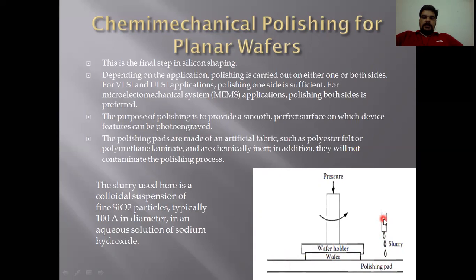These polishing pads are made of basically artificial fabrics such as polyester felt, or you can use polyurethane laminate, and they will not contaminate the polishing process. The slurry here is a colloidal suspension of silicon dioxide particles, typically 100 angstrom in diameter, in an aqueous solution of sodium hydroxide. So by this we can do chemical polishing.